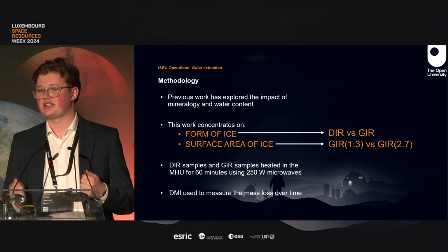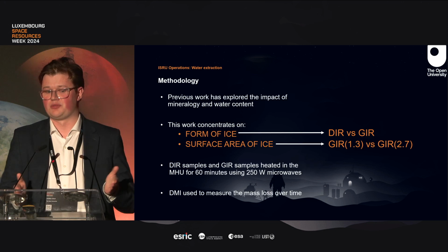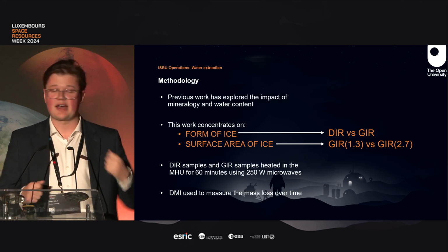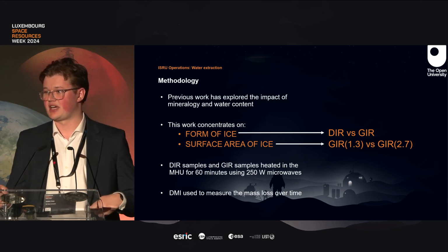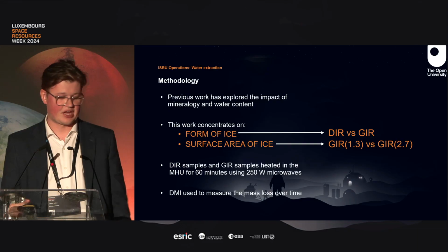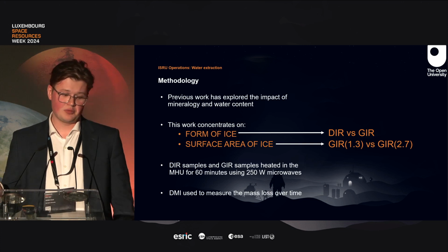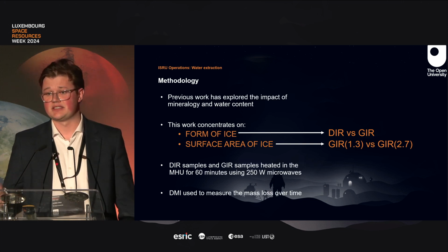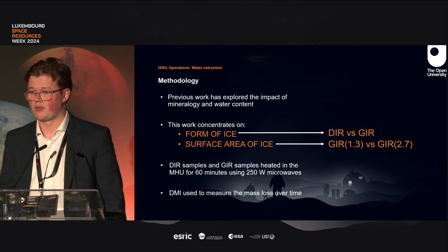With the diffuse ice, it's very difficult to gauge what the surface area of that sample is. So that's why I've got the two different grain size subsets, because I wanted to be able to easily quantify what the estimate of the surface area was. The samples were then placed in the microwave heating unit and heated for 60 minutes using 250 watt microwaves.